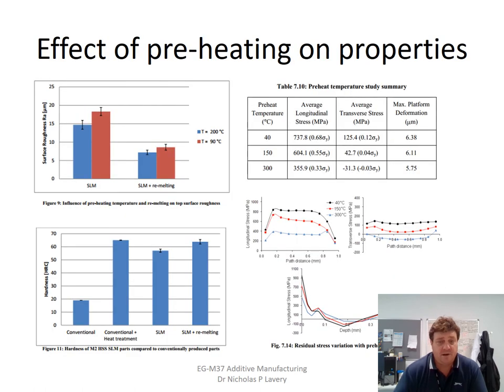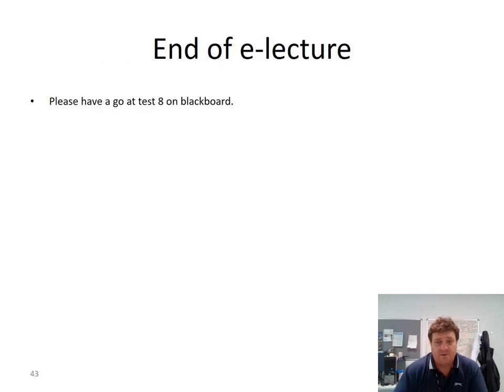That's something that we tend to keep on. It can also be shown that by preheating, you can improve the mechanical properties of the parts which are built. And it also reduces the residual stress, and it's particularly the residual stress that we're very interested in reducing in parts. We will tend to keep our heater on.